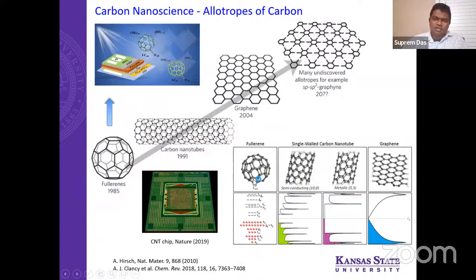physics. For example, if you look at the fullerene atom or molecule here, it has a band structure, say HOMO and LUMO type, people talk about that. And if you're a solid state physicist, you can think about a band gap, right? But if you have a carbon nanotube, it's a little bit more complex because you have so-called chirality. Depending on the chirality, it can be semiconducting or it can be metallic. Of course, if it is semiconducting, you have a band gap. But if it is metallic, as you can see here, your filled band is up to the Fermi level or beyond the Fermi level. So it becomes metallic, either this type or band overlapping, depending on the type of chirality. But basically, the bottom line is that you have enough charge carriers in the conduction band or above the Fermi level, whereas here you have a finite band gap.